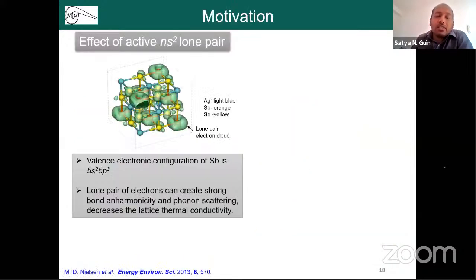Okay, so why is this system so important, why did you choose to work in this system? As I told you, you need to have very low thermal conductivity to get a good thermoelectric effect. That is why we chose this system, because it has a very different bonding type and electronic configuration, which helps to get an intrinsically low phonon thermal conductivity, which leads to low thermal conductivity in the system. It has a lone pair of electrons, like in antimony, s2 electrons, which results in huge lone pair electron clouds, which deform the bond arrangement and decrease the thermal conductivity of the system. And additionally, it has a disordered cation sublattice, which results in low thermal conductivity.